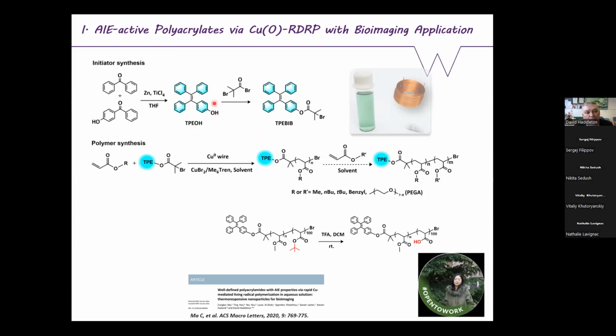Here we make these tetraphenylethylene with one alcohol by doing this pretty simple reaction. We then esterify that to make our initiator, and then we just grow the polymer from there, depending upon what we're going to do. In this particular case, we're using copper 0, hexamethyl-TREN, and a polar solvent, DMSO or IPA probably in most cases, and we can polymerize any acrylate. This is an acrylate, not a methacrylate, and then we polymerize that off. Our alpha end has the emissive group.